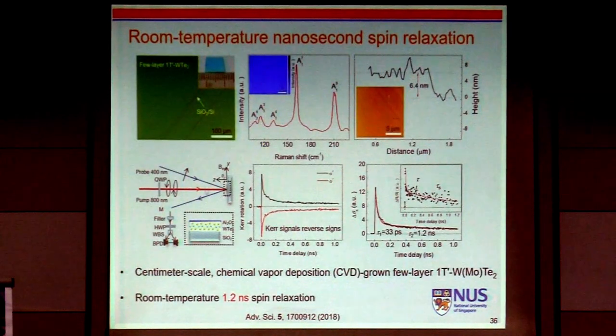We are trying to also measure the spin relaxation time constant using a magneto-optical measurement. And this is a CVD-grown film. This is an example of 1 cm by 1 cm from our collaborator. It's very uniform, and thickness is about 6 nanometer in this case. And we found the spin relaxation time is 1.2 nanoseconds. And this is about 1,000 times longer compared to topological insulator. So this material, I think, is very interesting. Very large spin-orbit coupling, yet very long spin relaxation time, even at room temperature, and large spin-orbit torque.